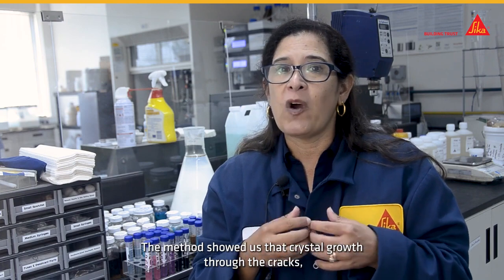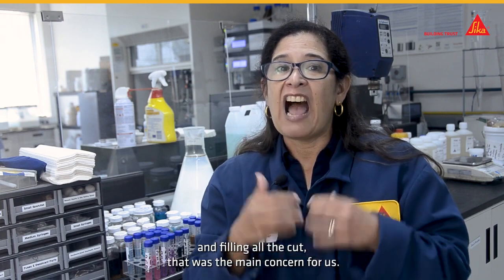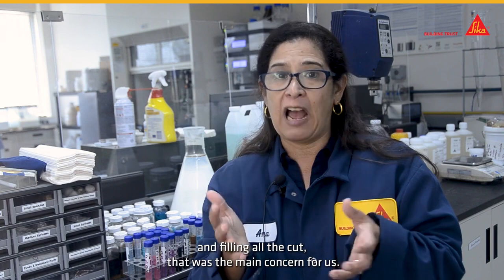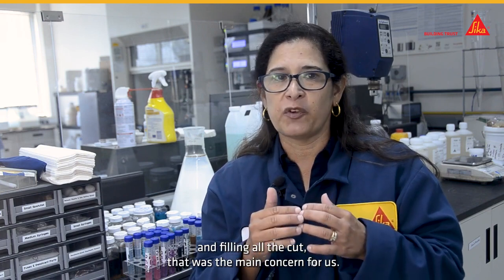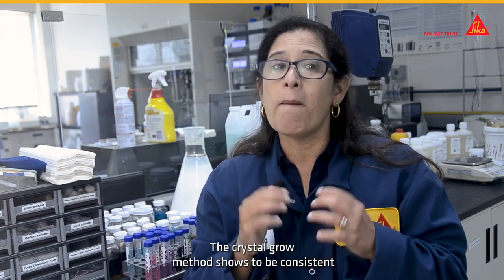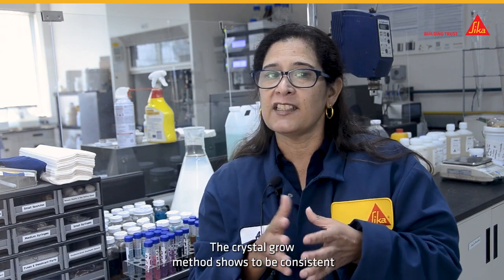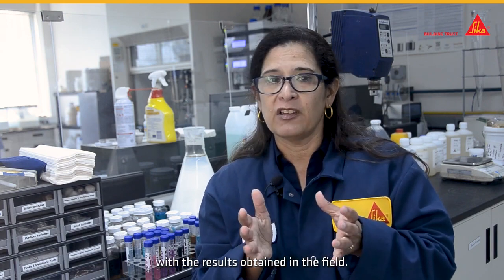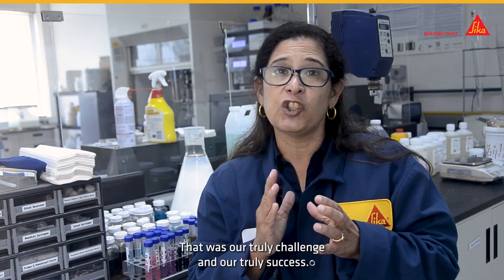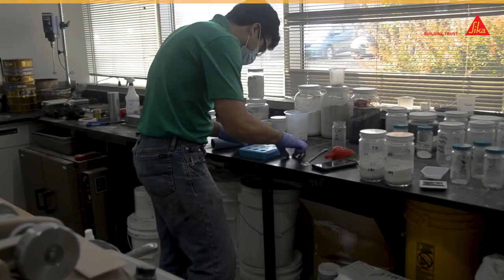The method showed us the crystal growing through the crack and filling the whole gap. That was the main concern for us. The crystal growth method showed to be consistent with the results obtained in the field. That was our true challenge and our true success.